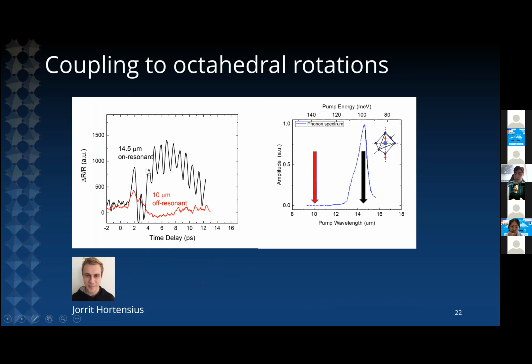And here we come to the first measurements that I would like to discuss with you. So this is a measurement of reflectivity as a function of time delay of a crystal of lanthanum aluminate. At time 0, we come with either a mid-IR pulse that is tuned in resonance with a phonon mode of lanthanum aluminate or not. So in blue here you see the phonon spectrum of lanthanum aluminate that has this peak around 15 microns, which is associated with a stretching mode of aluminium oxygen, which is visualized here.